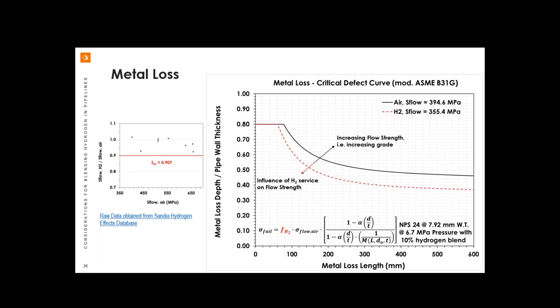So one possible approach for our fitness for service would be to simply introduce an additional partial safety factor for hydrogen service. Here I'm showing you the modified ASME B31G failure stress equation with that new partial safety factor. And what you can see is the influence of that new partial safety factor on our metal loss critical defect curve, allowing less, not so deep and not as long features. Of course, if we increase our flow strength, or had we had a higher grade, that is also pushing this curve in the opposite direction.